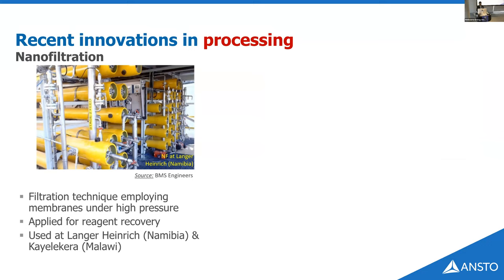In terms of other innovation in the processing space, you're looking at nanofiltration. Now, I'm quite sure lots of people are familiar with reverse osmosis, which is used in desalination plants. It's effectively the same principle, but at a lower pressure. You're looking at about 40 bar pressure here. What it does is basically allow monovalent and multivalent ion separation, and it's typically being considered and used for reagent recovery. So at Langer Heinrich, which is a carbonate-based operation, carbonate leaching, they're recovering the carbonate to send it back to the process. And Kayelekera in Malawi uses acid, and they're recovering acid for that.